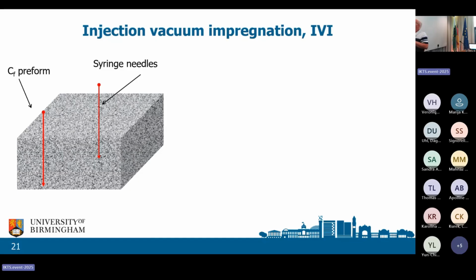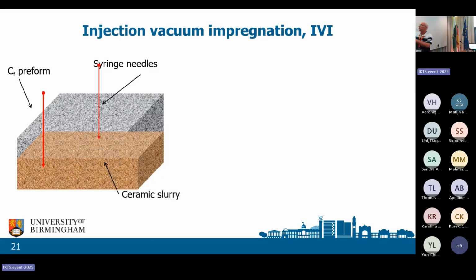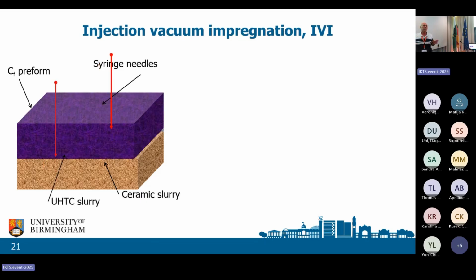That's no use. So we developed a process. This is Birmingham work. We developed a process based on injection. So you take your preform, whatever type, 2D, 2.5D, 3D, and then you plunge a needle in. And as you withdraw the needle, you're pressing down and squirting the slurry, and you squirt it locally where you want it. So you can put the ceramic slurry into your preform. Now, once you've developed that process, you say to yourself, well, do I have to always use the same matrix? Can I put different things in different locations?